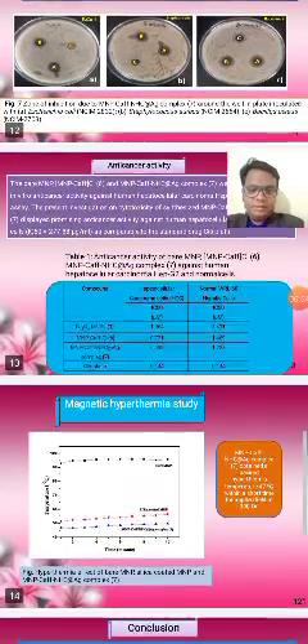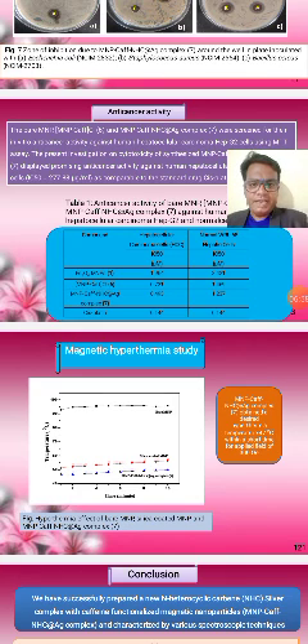We evaluated the in vitro anti-cancer activity using the MTT assay for the bare MNP, the precursor and the silver complex anchored on magnetic nanoparticles against hepatocellular carcinoma, which is one of the most important hepatic malignancies and accounts for the third highest number of cancer-related deaths. This complex is showing a very promising activity. From the IC50 values we can see that it shows very promising anti-cancer activity against hepatocellular carcinoma, and very importantly, this complex has low toxicity towards the normal hepatic cell line.